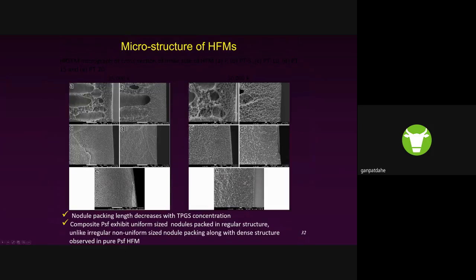So this is one of the studies we conducted. These are very high resolution scanning electron microscope images. This first image is at 25,000 magnification, and the second image is 50,000 magnification. As you can see, as I told you, the selective layer of the membrane consists of nodules. These nodules are the selective layer, a closely packed nodular structure of the membrane, and the spaces between these nodules are called the pores or pore length of the membrane.